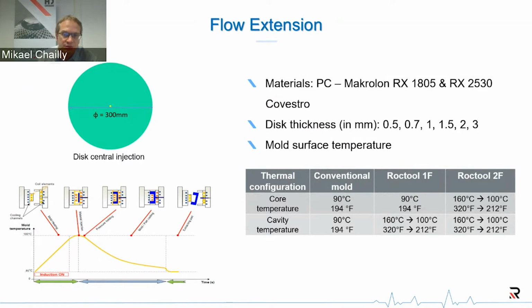We will not present all of the results, but a brief nutshell of certain results. In terms of mold surface temperature, we have considered three configurations. The first one being the reference for conventional molding, the mold surface temperature would be set up at 90 degrees C on both sides.